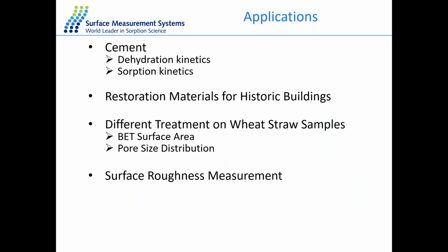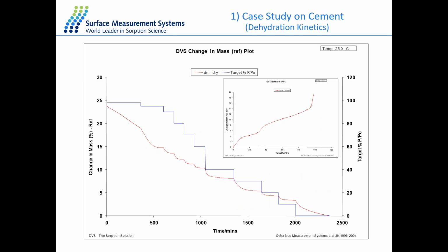And then we will go through different applications, and the first one is on the cement sample. So here we study the cement sample. We measure the desorption kinetics with the DVS method at 25 degrees. The same here, the blue line is the target relative humidity, and the red line is for the change of the mass. For this method, we start directly from 95% RH and decrease the humidity with 10% intervals, and then go back to 0% RH.